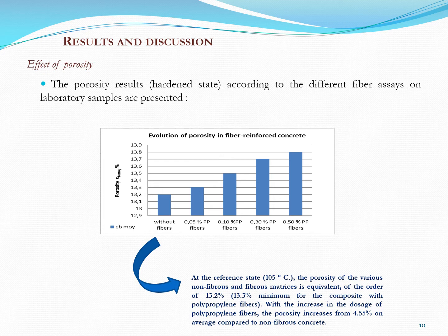In the reference state at 105 degrees Celsius, the porosity of the various non-fibrous and fibrous matrices is equivalent, of the order of 13.2%. With the increase in the dosage of polypropylene fiber, the porosity increased by 4.55% on average compared to non-fibrous concrete. As you can see in the figure, it is certain that the presence of polypropylene fiber in cementitious composites results in the connectivity of the pores of the composite concrete and consequently an increase in the pore volume, but this porosity remained low compared to the other matrices with other synthetic fibers. This is consistent with research on the porosity of cementitious composites.